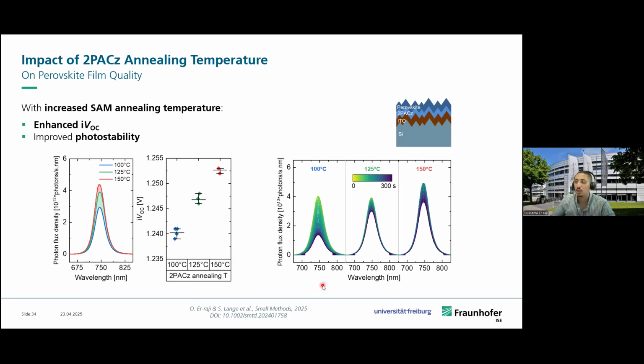And in terms of the interfacial quality with the perovskite, we again used PL measurements from which we extracted iVOC. And here you can see that with higher annealing temperature, we had a higher PL intensity, which was reflected in around 15 millivolt increase up to 150 degrees. And in terms of photostability, we tried to track the PL over a duration of 300 seconds. And here we observed an optimum at around 125 or 150 degrees. There was much less change compared to 100 degrees.